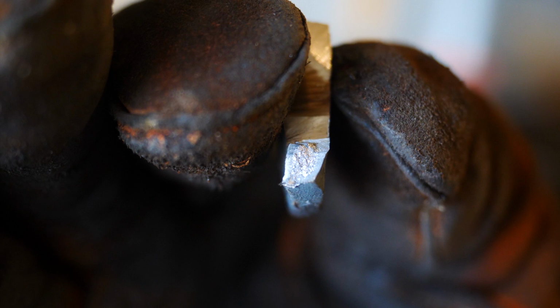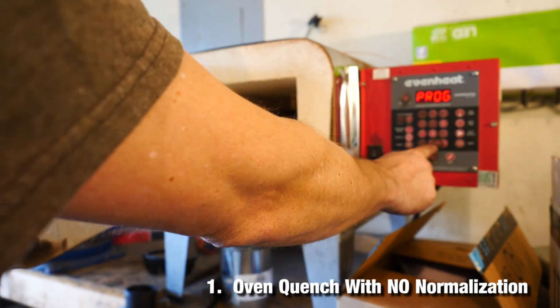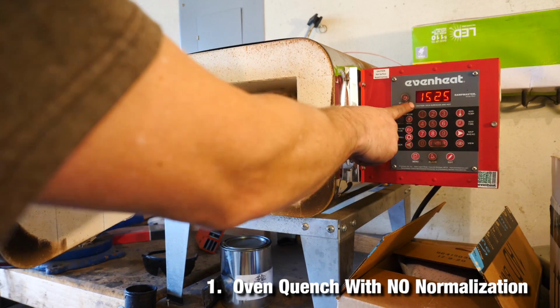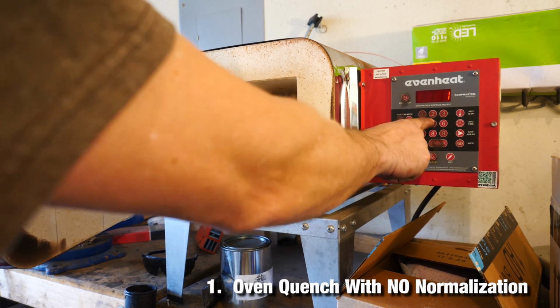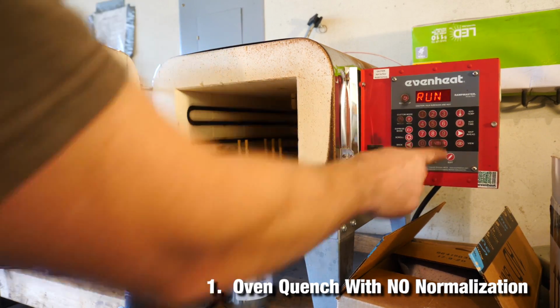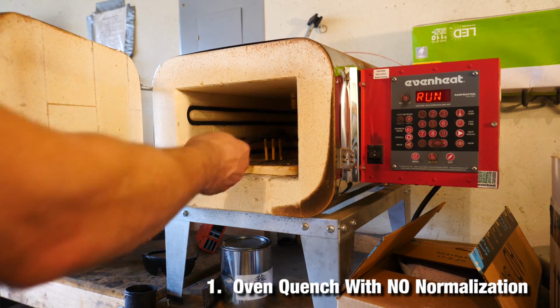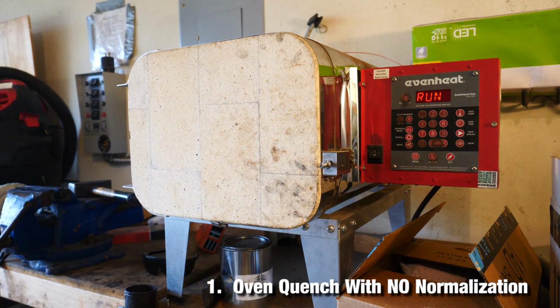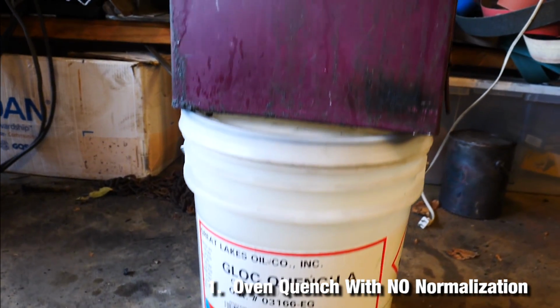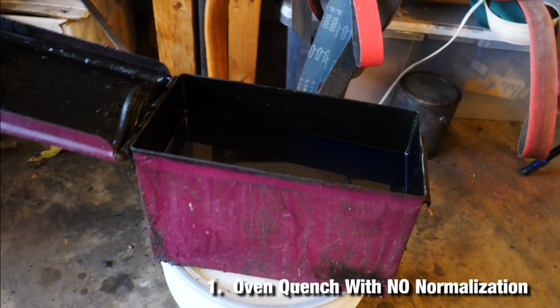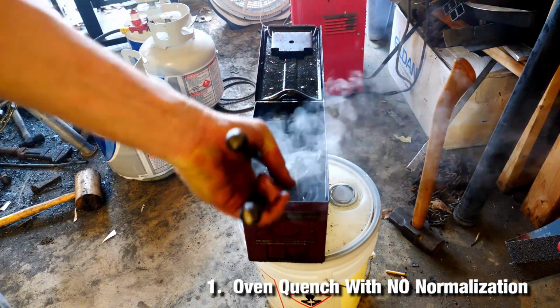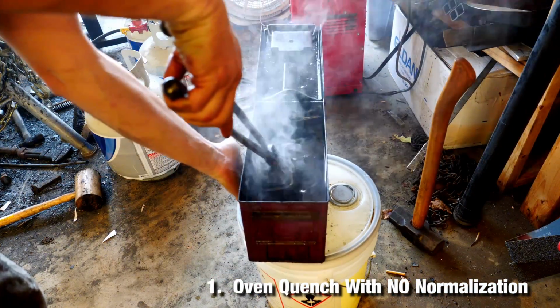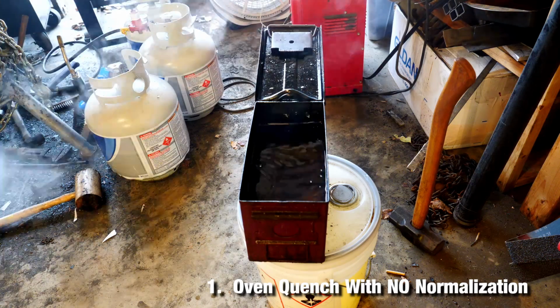So that's pretty big. Here we go with piece number 1. We're going to quench from the oven without normalizing our steel at all, but we're going to use temperature control and quench at precisely 1525 degrees. That's our quench A. It's a commercial quenchant. A slow oil.